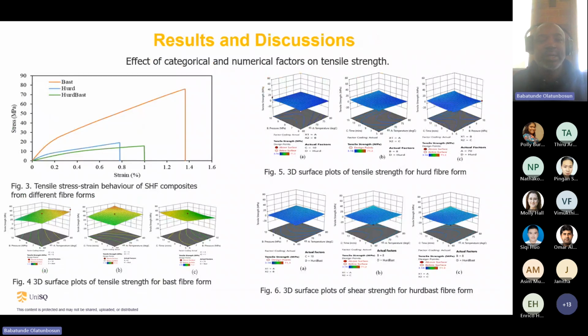Now for my results, the first result is the effect of the categorical and numerical factors on tensile strength. When I say categorical factor, I'm talking about the fiber forms. Figure 3 shows the tensile strength behavior of the sun hemp composites with different fiber forms. You see the bast has the highest tensile strength of about 71.9 megapascal, which is about 35% more than those of the hurd and the hurdbast. Comparing that value with the tensile strength of my resin, which is around 54.9, that shows the sun hemp can act effectively as a reinforcement material, not as a filler.